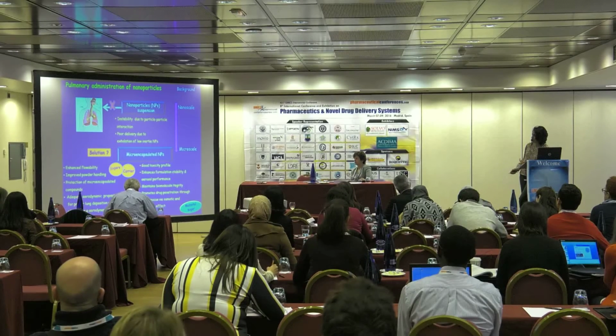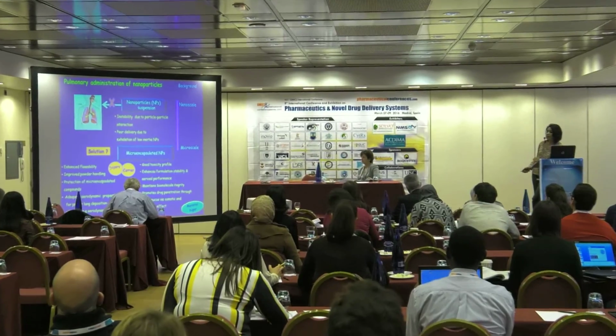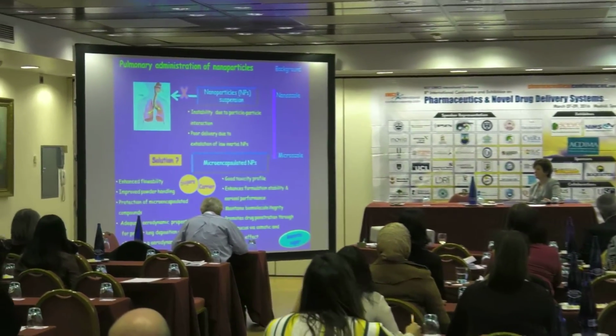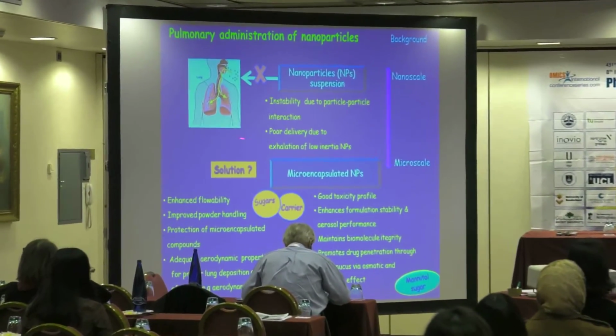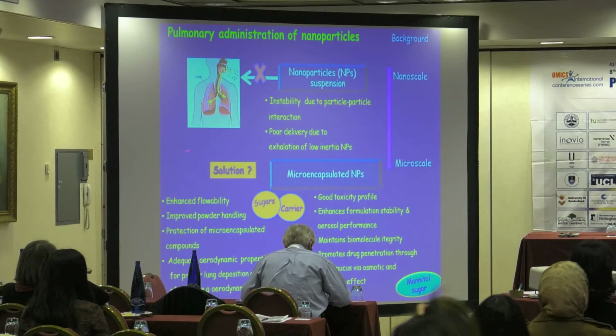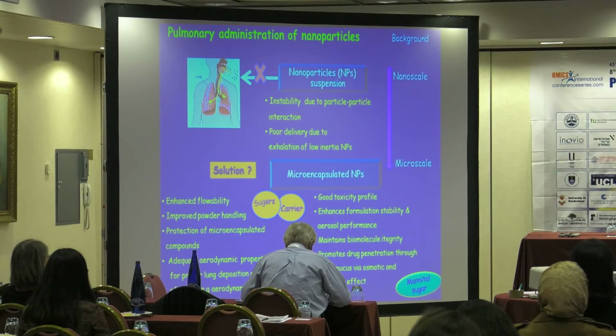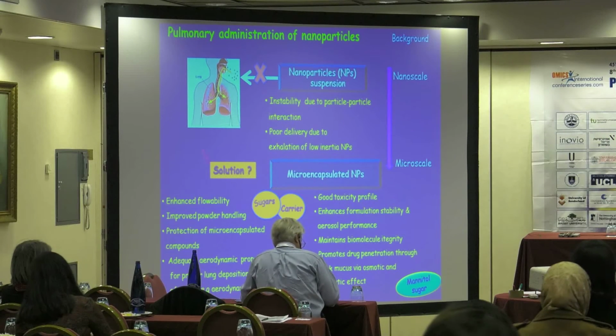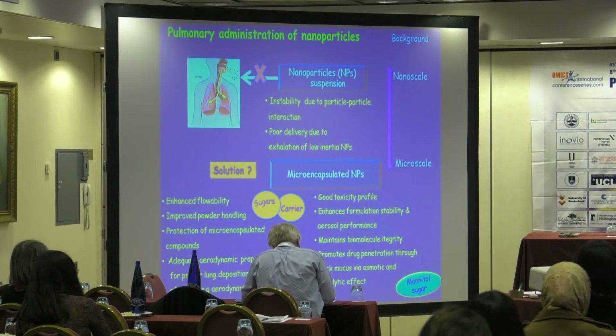To do this, we need carrier excipients, and usually people use different carriers like lipids, amino acids, and sugars. In our case, we used different sugars like lactose, saccharose, and mannitol, but in this study we used mannitol because of its safety record, and because it enhances formulation stability and aerosolization performance of the powder formulation.